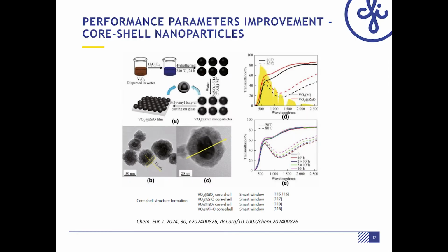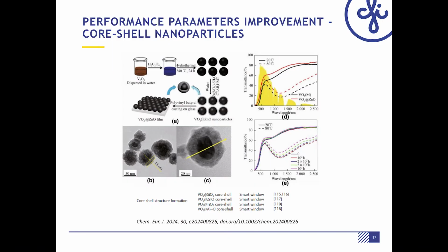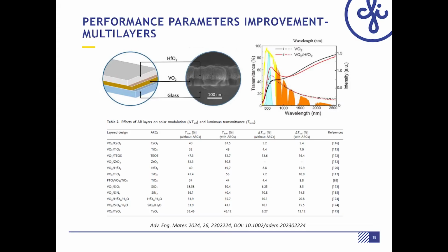In case of nanoparticles, to improve transparency and to increase environmental stability, core shell approach is used. Vanadium dioxide core can be coated with silicon oxide, zinc oxide, titanium oxide, and aluminum oxide. One more method to improve thermochromic parameters is multi-layers or anti-reflecting coatings. What is nice about this method, it helps not only to improve transparency, but also to improve solar modulation.